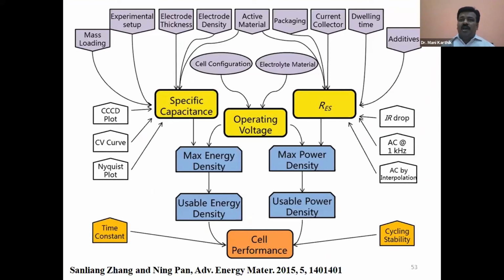I would like to point out here, most of the people are working with 1 mg, 2 mg coating on the surface. At laboratory level with 1 mg, 2 mg, there is a lot of problem in measuring the weight also, because even with a balance, weighing 1 mg has a lot of error, at the student level I am talking about. So from that 1 mg, 2 mg weighing itself, you lose a very small milligram and your error is very high. If the error is very high, your final calculation is wrong, so you are misleading about your material performance.